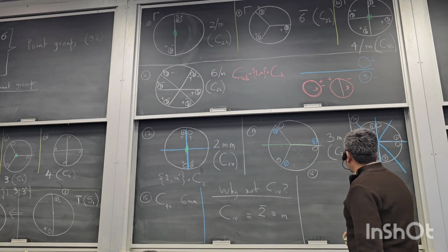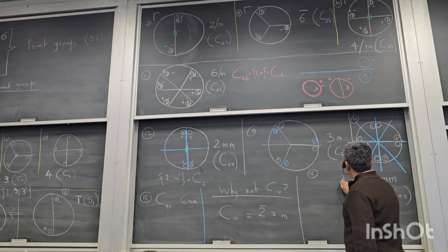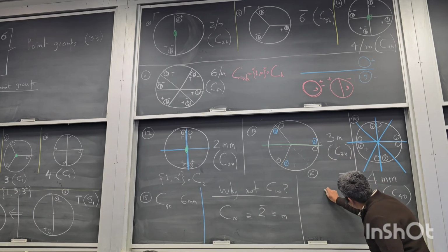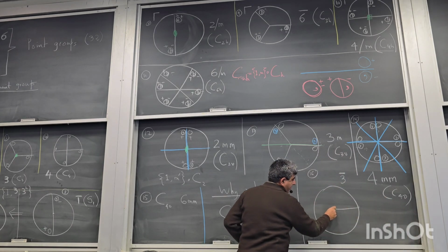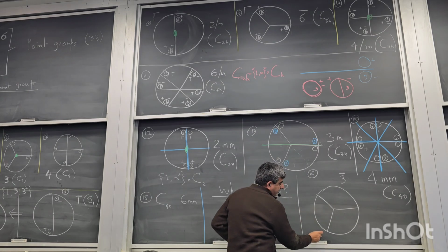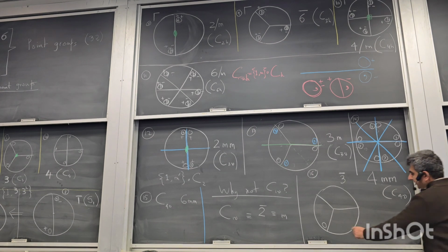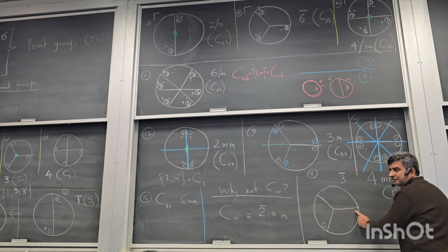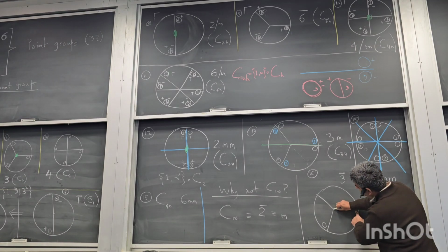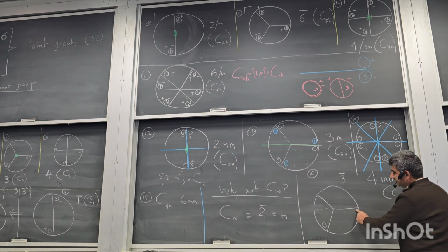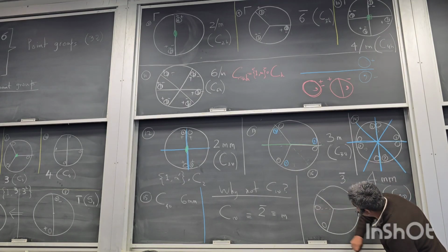having a 3-bar operation. Let's see how this is formed. I have an object here. I do a 3-fold rotation. This object lands here. But I really need to follow this by an inversion about this point. So an inversion of this point lands me here. If this is plus, this becomes minus with a comma.